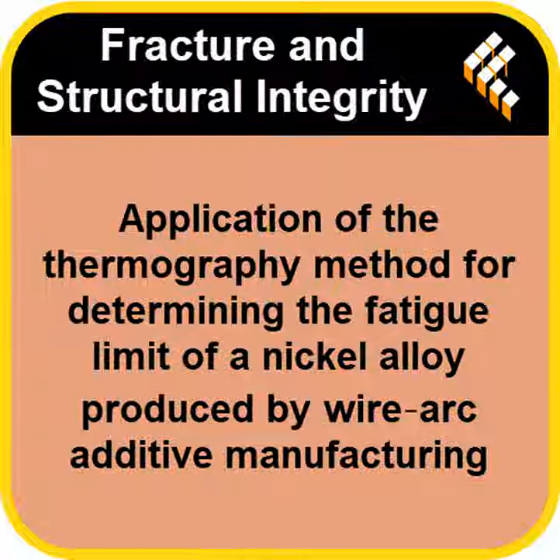And what did the gold standard, the time-consuming test, finally reveal? The traditional fatigue limit, based on a 50% chance of failure at 10 million cycles, came out to be 399 megapascals. Okay, so 383 versus 399, a difference of 16 MPa. That's really close. It is. And the crucial takeaway here for you, the listener, is the percentage difference. The accelerated result was only 4% lower than the traditional one.